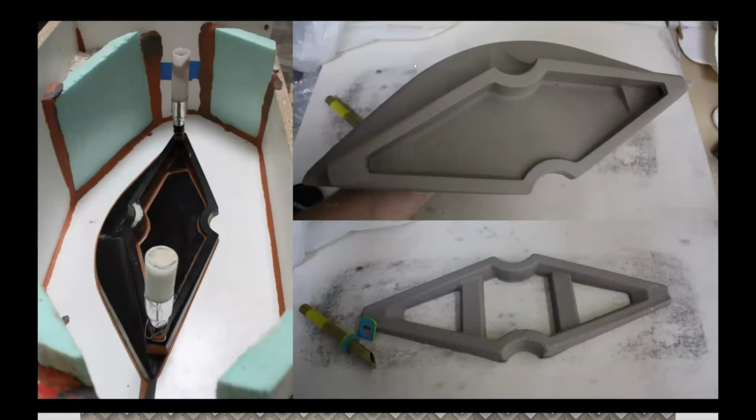These are some images of the process. We are in the slip cast portion of this presentation, but we also designed this terracotta piece to be ram pressed, with the idea being that if we are deploying this across an entire facade, it would be fast to ram press it. So in designing it, we made sure we didn't have any undercuts. You can see that the back here is hollowed out to reduce the weight, since this entire system is suspended by a tensile structure. The goal was to have it be as light as possible, and also to distribute the weight in the module itself to allow it to pivot without putting too much strain on the pins themselves. Next.